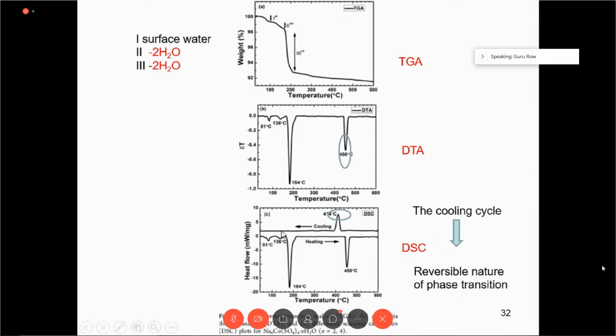We also see that on the cooling cycle in the DSC, the original compound, that is the anhydrous compound, comes back and stays at room temperature. So we take the mineral, heat it up, lose two water molecules and two other water molecules, get the phase which we would require, heat it to 450 degrees, get the superionic conductor. The superionic conductor now becomes a normal ionic conductor, and on cooling, it goes to room temperature. So here is the situation. We have a reversible phase transition, and this is very interesting to observe.